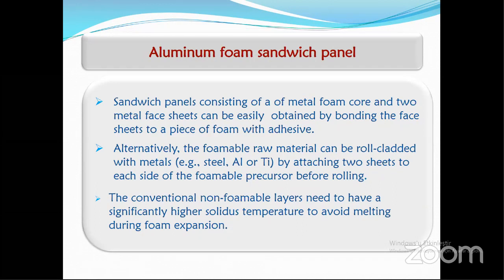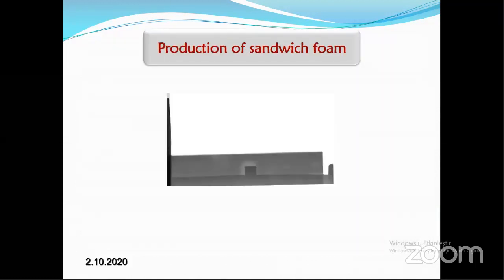by attaching each side of the foamable precursor before rolling. We are doing that one actually. The conventional non-foamable layers need to have a significantly higher solidus temperature to avoid melting during foaming expansion. Otherwise, the cover layer also melts. This is the production of sandwich foam. That's also a good video. In both sides of sandwich, non-foamable metal. The inside core is foamable material.